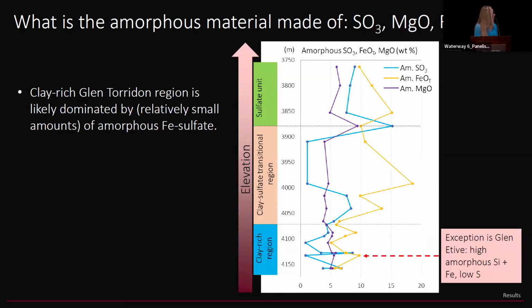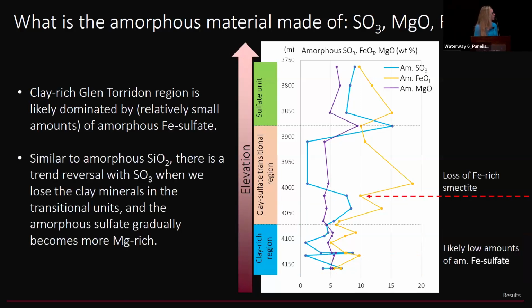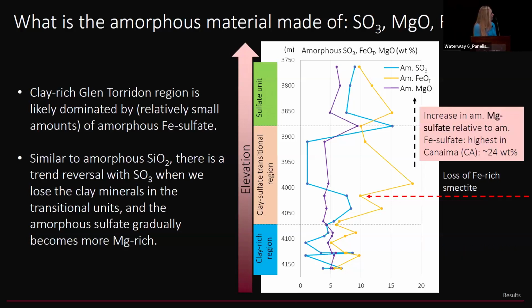And I think the largest sample with the most amorphous sulfate is Canaima. So this again happens when we see this trend reversal with iron and silica as well. So I think that this is really telling us something. So again, this is where we lose the clays and the samples start to become more magnesium sulfate rich. Canaima had the largest amount of amorphous magnesium sulfate, which was around 24 weight%.